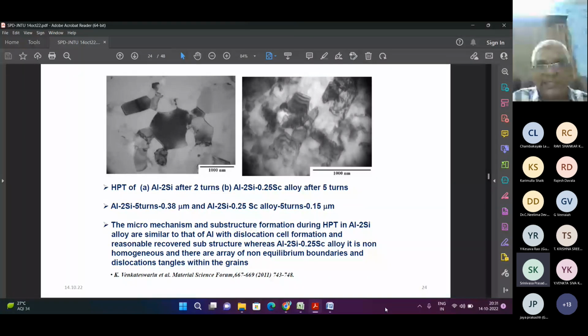On the right side, you can see the dislocation pattern, how dislocation pile-up is taking place and making different grains. You can see three grains forming within the dislocation loop. You can also measure the dislocation distance. Aluminum 2 silicon after 5 turns gives 0.38 microns, less than 1 micron. Aluminum 2 silicon 0.25 scandium after 5 turns gives 0.15 micron, almost half of that. So the influence of scandium content can be understood from these images.